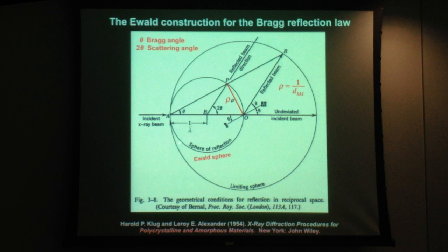So with respect to the diagram, it is as if, while the crystal is rotating here to give us these diffracted beams with incidence and scattered angles theta, this rho vector is rotating about here. So we imagine a three-dimensional constellation of these rho vectors for different angles theta. While the crystal is rotating to bring each of those families of planes into view, the normal to those planes is being brought into position to cut the Ewald circle or Ewald sphere, the sphere of reflection.